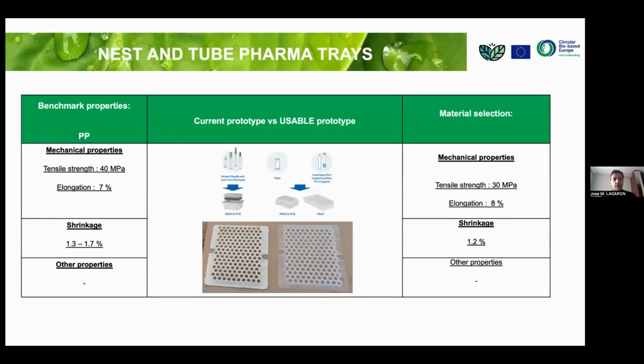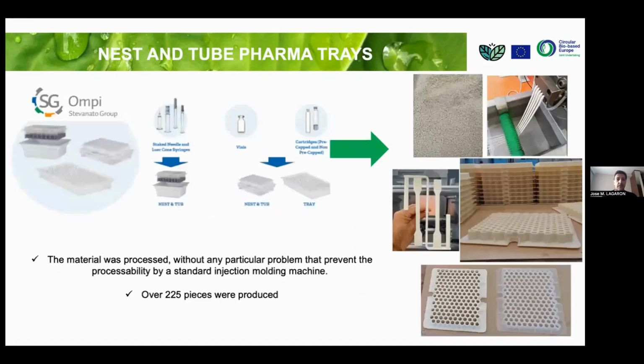Nest and tube pharma trays were also developed by injection molding, and it was extremely amazing how the team involved was able to match the mechanical performance of the existing product based on polypropylene. Even the shrinkage performance was lower than the existing one, and the large company was very pleased. They said that the material processed very well, and they would see no issue using it in their conventional injection molding machines. Over 225 pieces were produced. Of course, in this case, we could not use the polymer derived in the project because they had to use 100 kilos. It was a 100 kilo application.